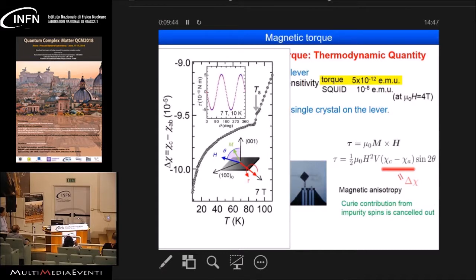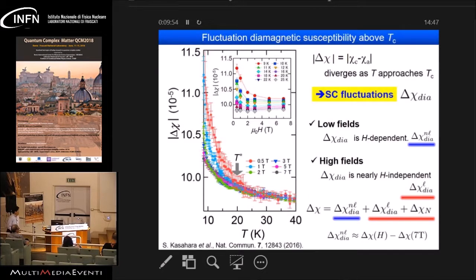And here is a plot of the temperature dependence of delta chi. And as you can see, we have an anomaly at the structural transition at Ts, which is expected. So we can plot the temperature dependence of the magnitude of delta chi at different fields. And as you can see, below about 20 Kelvin, which we call T star, it starts to have a strong field dependence. And this strong field dependence should come from the superconducting fluctuations, which is actually a diamagnetic susceptibility signal.